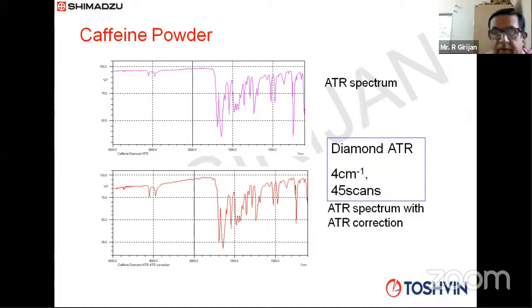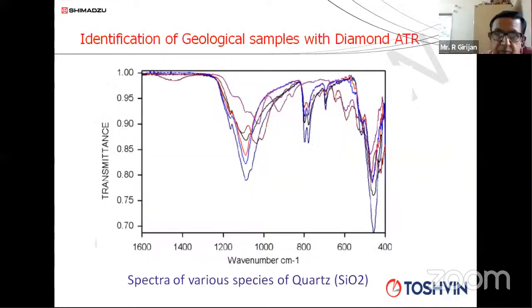Here again, I'm showing an example of the same material, caffeine powder, analyzed on a diamond ATR. And you are getting exactly the same spectrum as if you had prepared a normal potassium bromide pellet. You are getting the same quality of spectrum, and at the same time it's much easier. How much sample quantity do you want? You hardly require about 1 or 2 milligrams of sample. If it's a liquid sample, you need a tiny drop. The sample quantity is much reduced in the case of a diamond ATR. So diamond ATR has also become very, very popular.